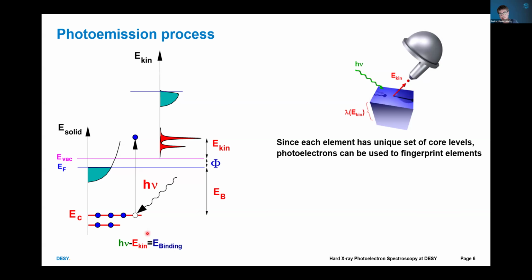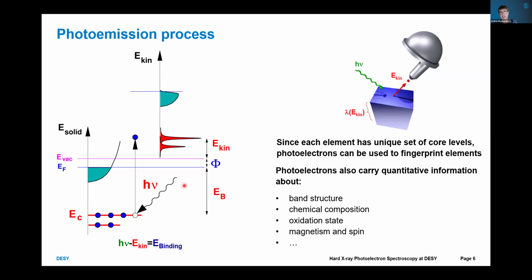And since each element has a unique set of core levels and core level energies, the photoelectrons are the fingerprint of elements. So we can do non-destructive chemical analysis of our sample. And photoelectrons carry quantitative information about other goodies like band structure, oxidation state, magnetism, and spin of the materials, and many others.